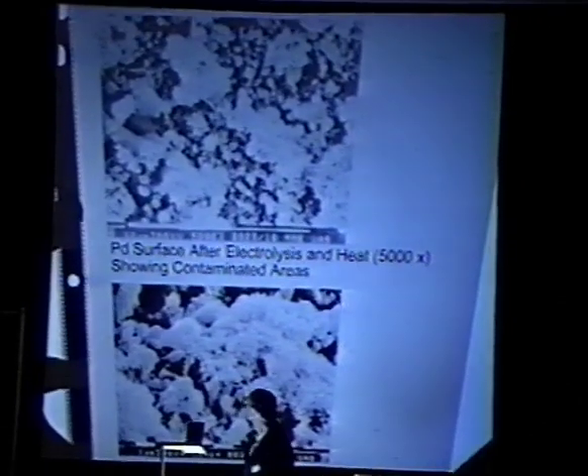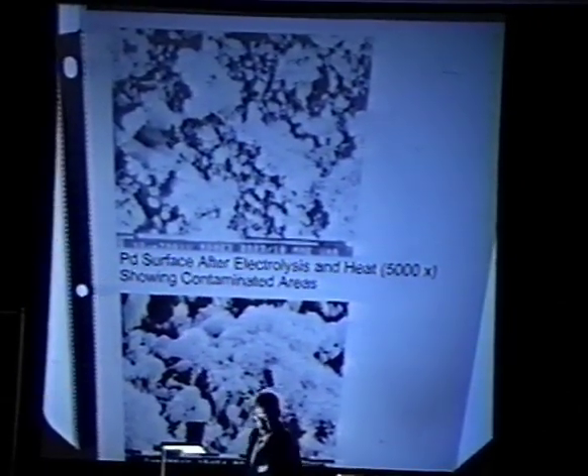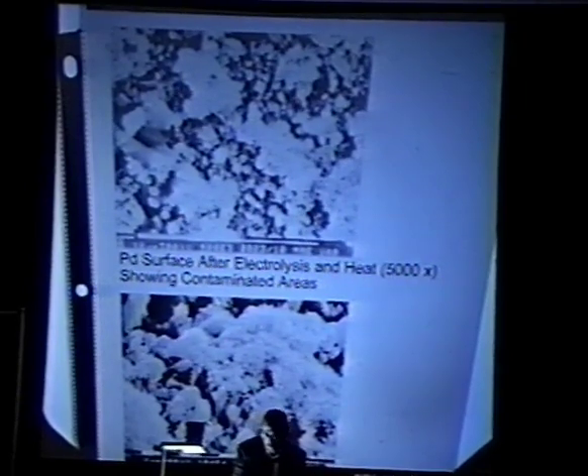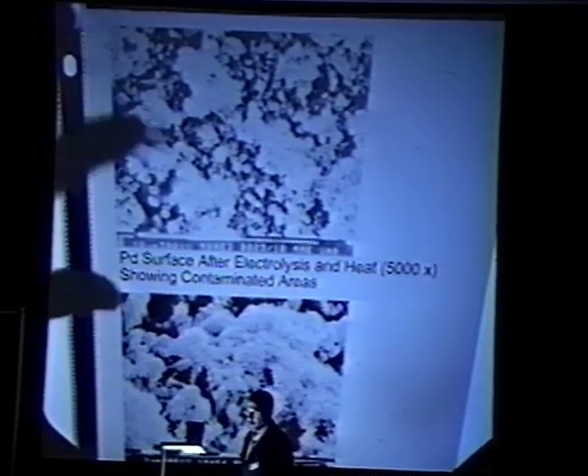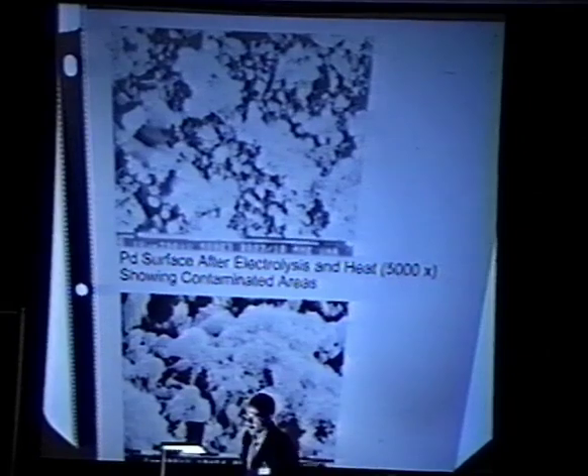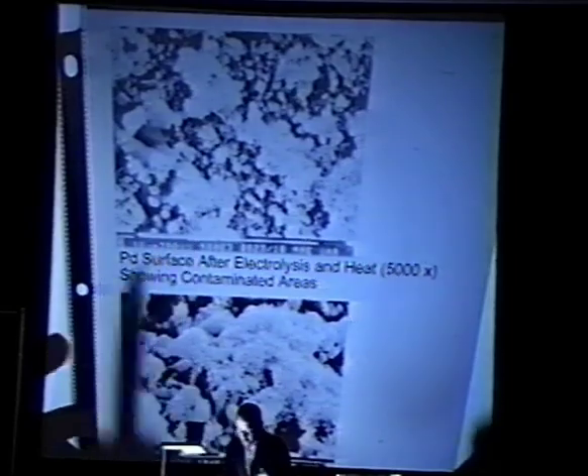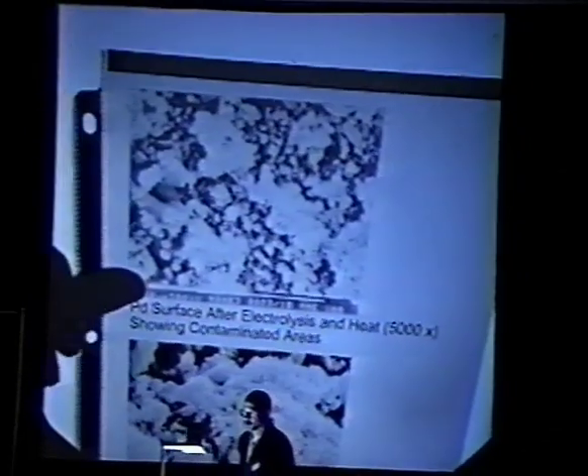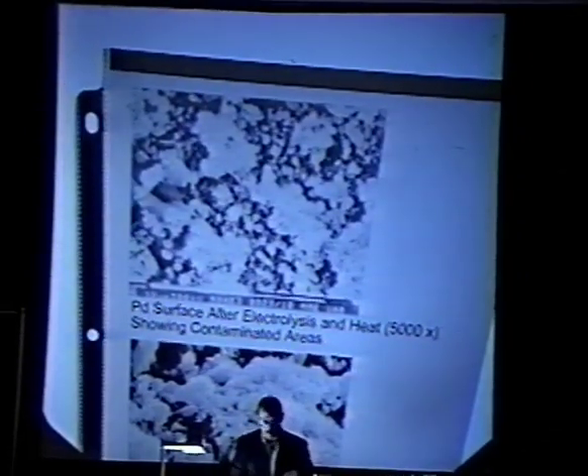Now, to give you an idea of several of these after electrolysis and after producing heat, this is one. Again, this is just a photograph of the surface. Just to give you a scale comparison, this top one is on a 5,000 times scale. Again, you see the 10 microns is roughly from here to here. And if you compare with this, 10 microns is roughly on the same scale, 1 inch or so across there. So what we're seeing is those grains completely covered up with a whole lot of stuff.